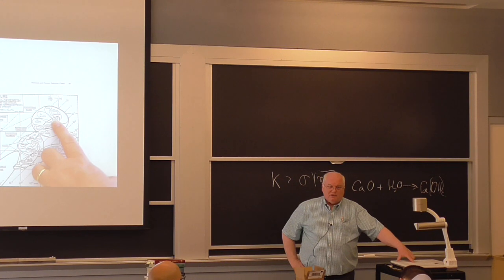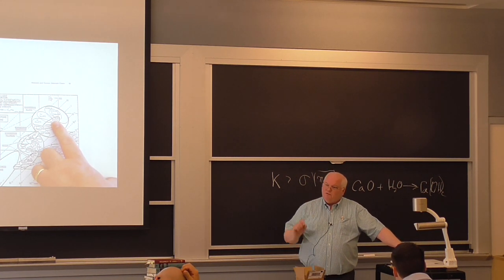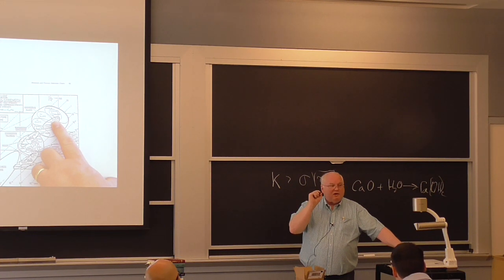We're going to talk about some of this stuff when we get to it. But the weld metal was 30 or 40% higher strength than it was intended to be because of the chemistry of the weld metal. And they got a less tough steel that formed little microscopic flaws that the original inspectors weren't looking for, something that small. It was a different type of cracking that we hadn't seen before.